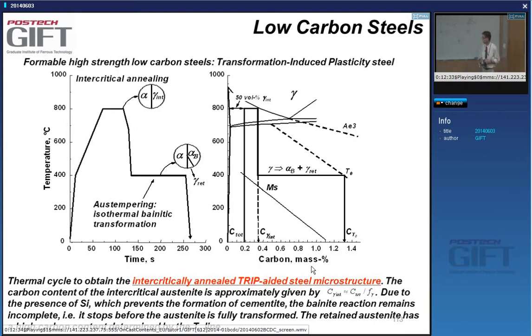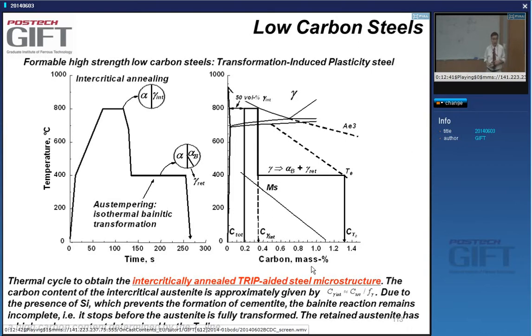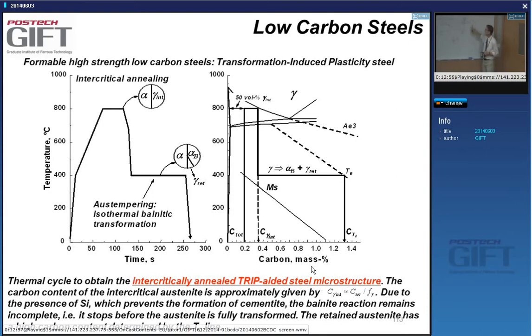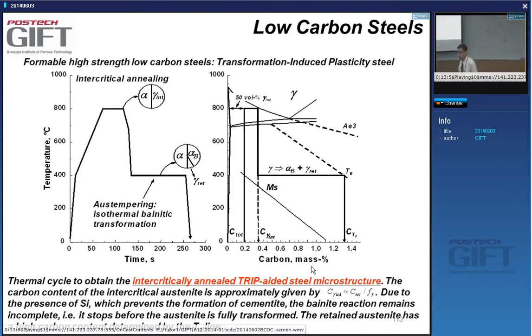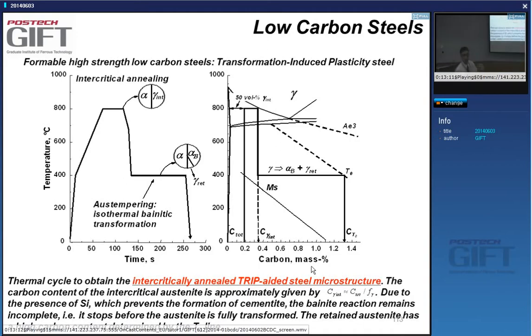Can you go beyond the T0 point and increase the carbon content further? No. Because if you would do this, the austenite becomes more stable than the ferrite, so it stops there. The austenite doesn't fully transform to bainitic ferrite because it keeps getting carbon from the transforming ferrite.